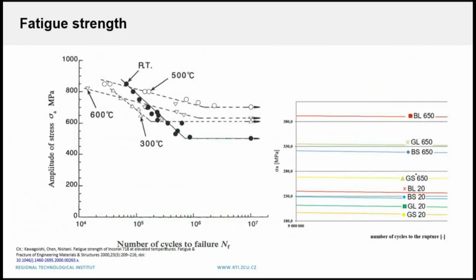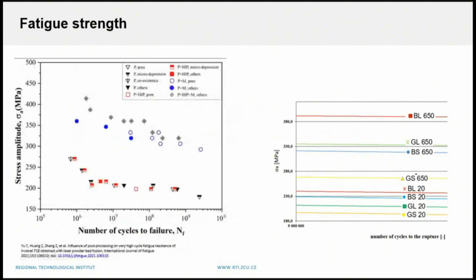And why? We compare it with standard data. Here you could see the standards from the normal samples which are machined, and the fatigue life of course increases. So we can say that we are 2 times lower than the other systems. Here you could see that when the materials are not machined, we are close to our results. But we have machined the outer surface, while the internal surface is not machined.